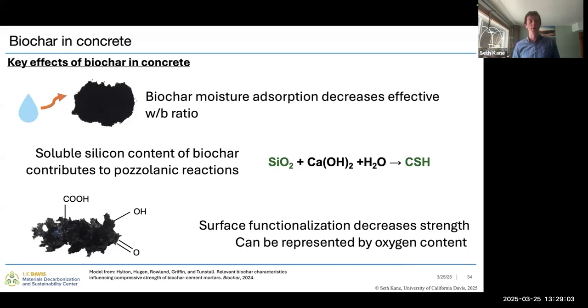This is from a paper out of Colorado School of Mines and National Renewable Energy Lab, who did a really great job of systematically looking at what are the effects of biochar in concrete. How can we modify the properties of biochar to maximize that performance in concrete? And the three key outcomes they found were that biochar will absorb some moisture from your concrete mixture, and that's going to decrease the effective water to binder ratio in that mixture. We know as that water to binder ratio decreases, our strength will increase, but it gets harder to work with. And so we really want to find a balance, integrate this into our concrete mixture design so that we can maximize those properties and get as close as we need to our designed properties.